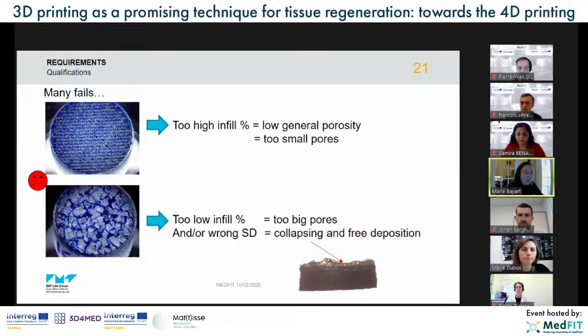So in the next slide, you can see we did qualification. We tried different parameters and we had many failures. Here you can see that in the first picture, we have a too high infill percentage, so we have a low general porosity. We've got very small pores, so this is not good for the cells to exchange fluids and nutrients. In the other one, we've got a too low infill percentage, we've got very big pores, and also we chose the wrong slicing distance. So we had a big collapsing of the structure and also free deposition. So the structure is not good at all.